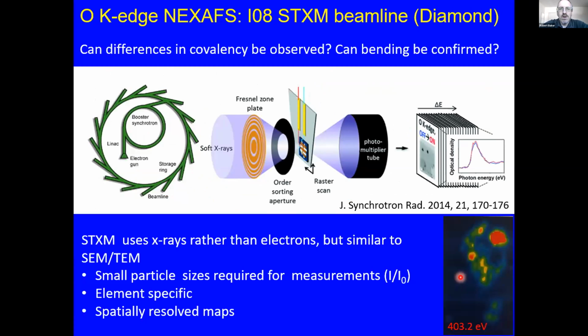So can we use oxygen K-edge spectroscopy to observe differences in covalency? And can we confirm the bending? Now, we've never been able to grow single crystals of these compounds, so we haven't been able to use more conventional soft X-ray spectroscopy under vacuum. So we were able to actually do these measurements using the STXM beamline at Diamond.